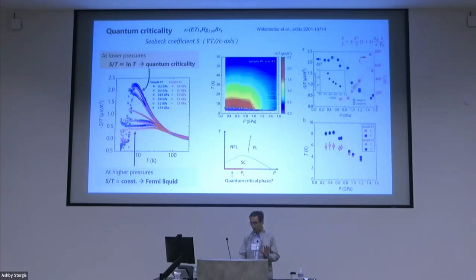So the temperature is decreasing with pressure, and in this region, the non-conventional behavior is observed in resistivity, pure T-linear behavior. In this region, S over T is very large, and on top of that, the temperature dependence is roughly log T. Log T is very common in quantum criticality.